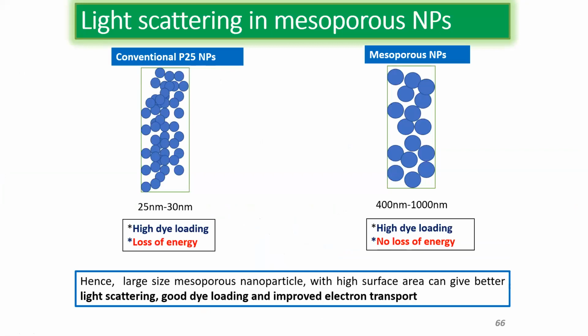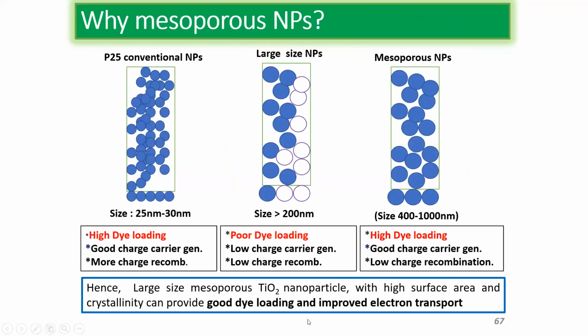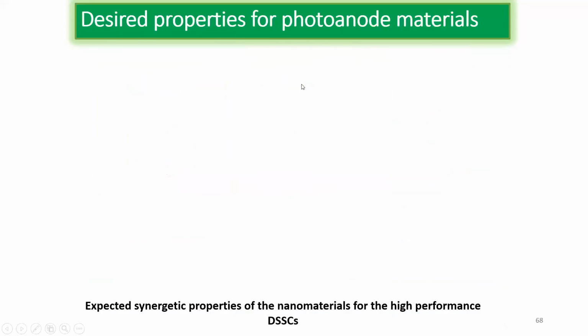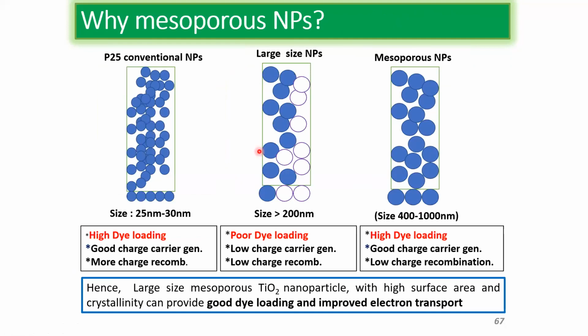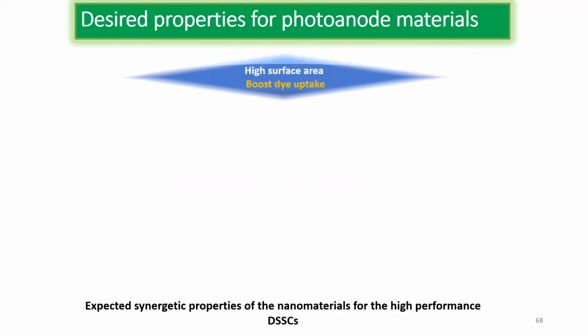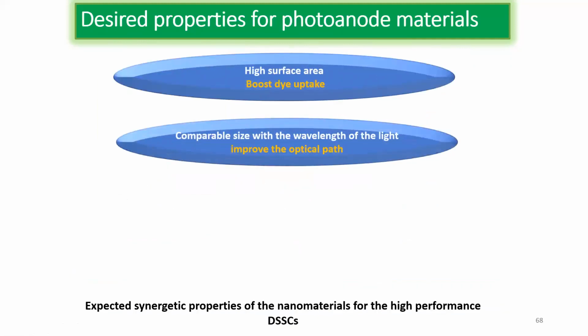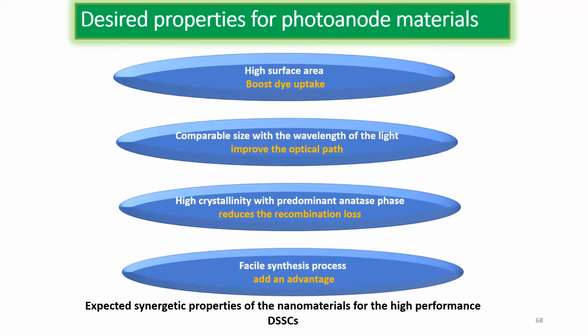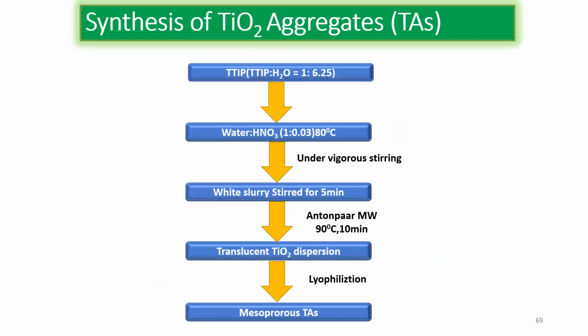But overall, when particle size is big, absorption will be better. So I wanted to have big particles, but the problem with big particles is the dye loading. Dye loading will not be proper. Dye loading will happen only at the upper layer, and the bottom layer dye loading will not be good. So I have to create mesoporous particles, so that I can have better dye loading. With all these protocols, I decided that we can have better surface area and better size of the material, and we can make a microwave synthesis protocol to generate this type of particles.